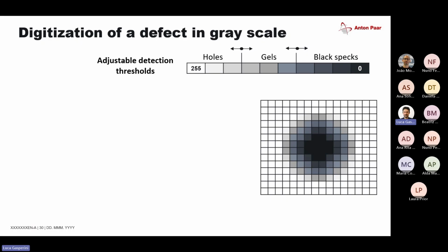So what the software does, it detects a scan of the whole line on the whole spectrum of gray levels, which goes from 0 to 255, and then based on the gray level, which is different from the baseline of your polymer, you can differentiate between different defects. So for example, very bright spots are simply spots where the lighting from below shines through, and they are characterized as holes. Very dark spots are considered as black spots within the material, because there is no lighting at these points, and everything in between is then classified as gels.